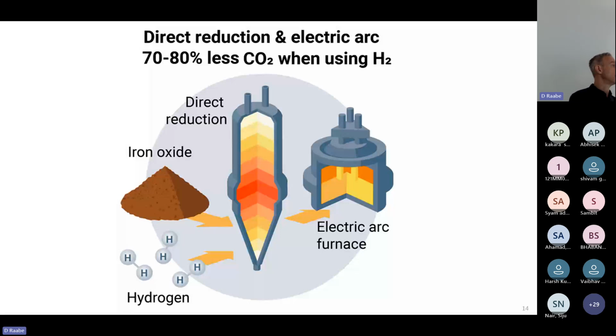And the balance is that you can operate that with 70 to 80% less CO2 emissions when you use hydrogen, but we all know that is a bit of an apples-and-oranges comparison when we don't have a fair estimate of what the CO2 costs are from the grid for making the hydrogen in the first place. So the second aspect that we have to keep in mind, that's why we have to take this very broad research approach across different technologies in the next decades, is that this amount of sustainably produced hydrogen is simply not available. For the 1.9 billion tons of steel produced per year, you would need something like 250 to 270 million tons of hydrogen every year, and that simply does not exist, as you know.